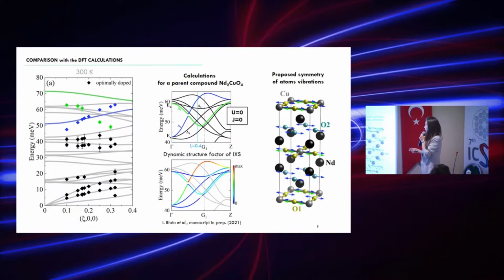And that's data for optimally doped sample. As you can see, the data follows calculations nicely, except for these two highest phonon branches, so the ones for which the anomalous softening was reported. Calculations marked on this picture by gray lines are calculations for parent compounds, so the antiferromagnetic one. And that was our first thought, that maybe that's the reason why these two branches don't correspond nicely to the calculations. And what we did, we changed a little bit our approach for calculations.